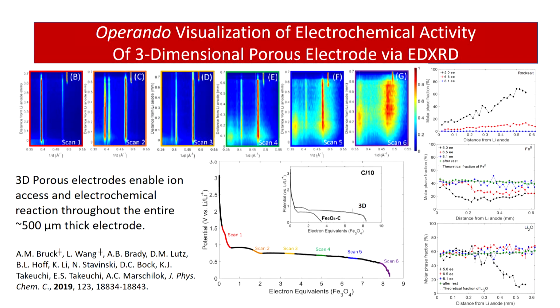So here's an example of a three-dimensional porous electrode. Again, probed via ED-XRD, and if we conceptually envision that we need ion transport throughout the electrode, then this is an example of getting full utilization and formation of iron metal throughout the electrode. And if we compare the capacity that we can obtain in a very thick 500 micron thick electrode that's densely packed versus a 3D electrode, we can see that there's really a difference in utilization of the active material.